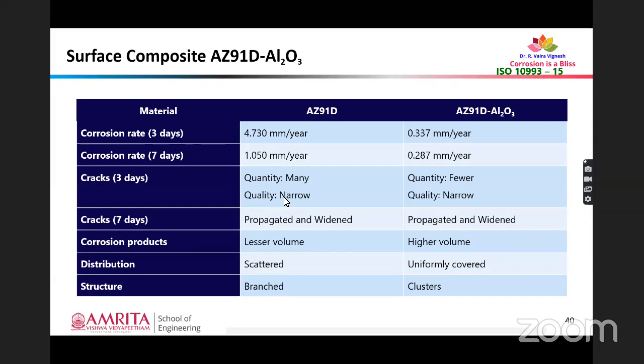So after 3 days, the base material had a corrosion rate of 4.7 mm per year, and the corrosion rate of the composite that we have fabricated is around 0.337 mm per year. The corrosion rate after 7 days came down to 1.05 mm per year in the base material, and it came down to around 0.287 mm per year in the composite.